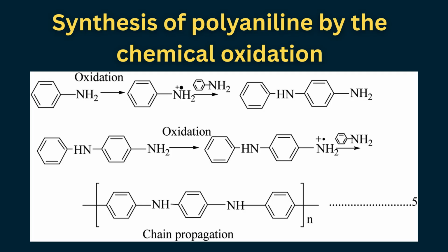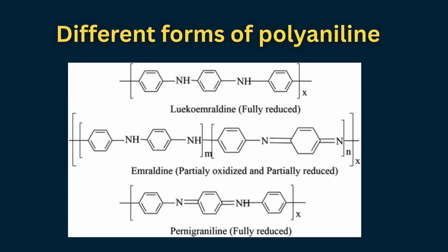PANI exists in three idealized oxidation states: leucoemeraldine, fully reduced, poorly conductive; emeraldine, partially oxidized, most stable and conductive upon acid doping; pernigraniline, fully oxidized, poorly conductive even after doping. Synthesis typically involves oxidative polymerization of aniline using ammonium persulfate in acidic media. The process is exothermic and yields a mixture of oxidation states, with acid-doped emeraldine being the most conductive and stable form. Organic-inorganic PANI nanocomposites enable control of electrical, magnetic, mechanical, and thermal properties.